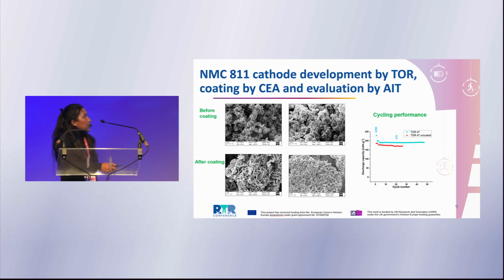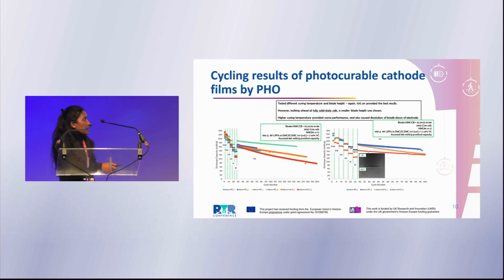So to develop the most surface contact with the solid polymer electrolytes, all the cathode materials prepared in this particular project were coated with different binders, and you can see the performance also. The uncoated material is lower compared to the coated materials. So these coated NMC materials prepared in-house in the project will go further to the photocurable catholyte formulations, which is led by Photocentric.